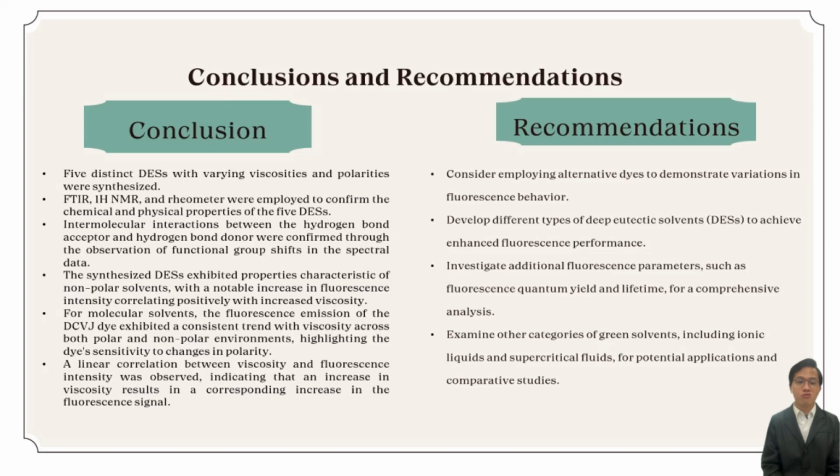rheometer techniques to confirm their chemical and physical properties. The spectral data reveal shifts in functional groups, confirming intermolecular interaction between hydrogen bond acceptor and donor. The synthesized DES exhibited properties characteristic of non-polar solvent with a notable increase in fluorescence intensity, positively correlating with increased viscosity. For molecular solvents, the fluorescent emission of the DCVJ dye displayed a consistent trend with viscosity across both polar and non-polar environments, underscoring the dye's sensitivity to changes in polarity.